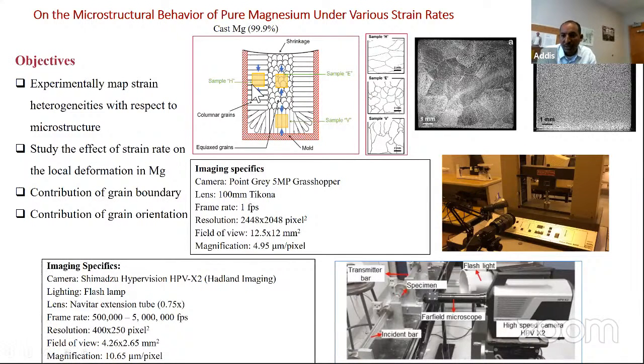What we did is we took pure cast magnesium and cut specimens at different orientations. If you cast material like this, you could have specimens where the grains are arranged horizontally, you could have grains arranged vertically, and you can also have grains in somehow isotropic type configurations. We used both quasi-static as well as dynamic experiments.